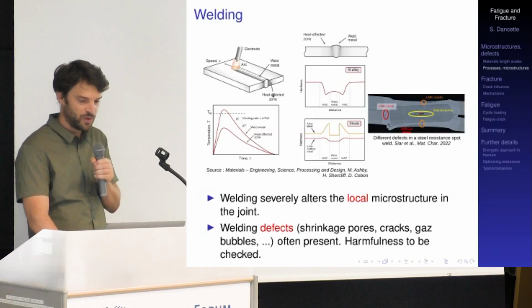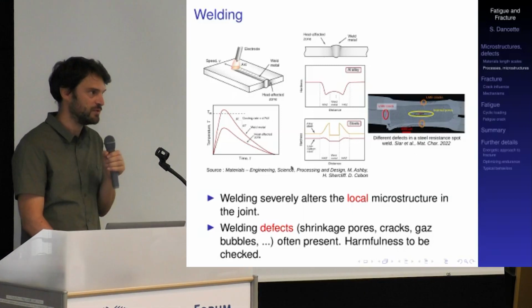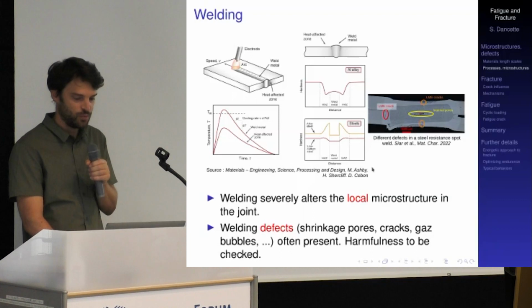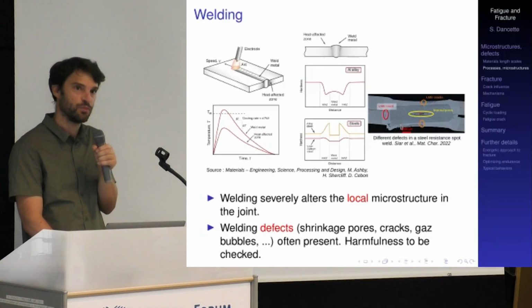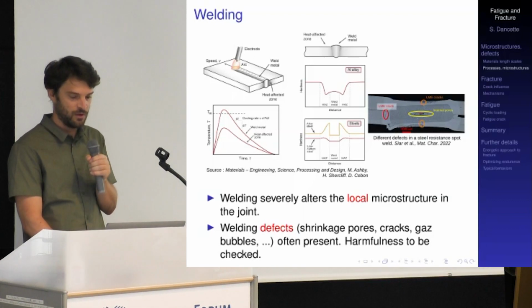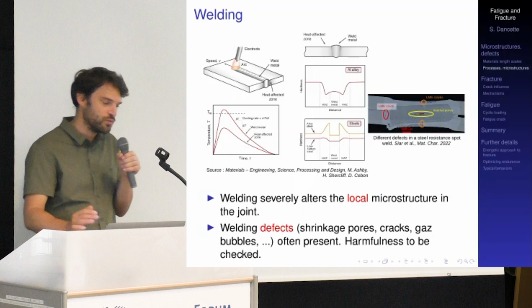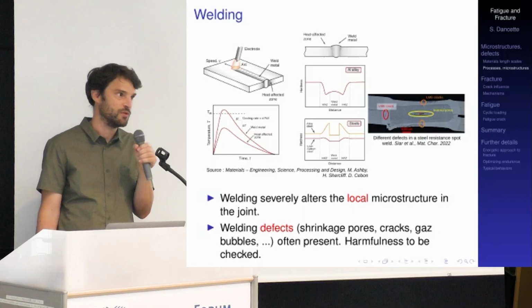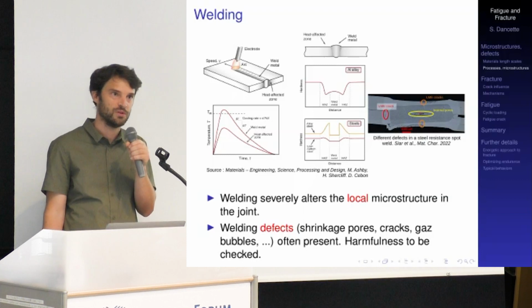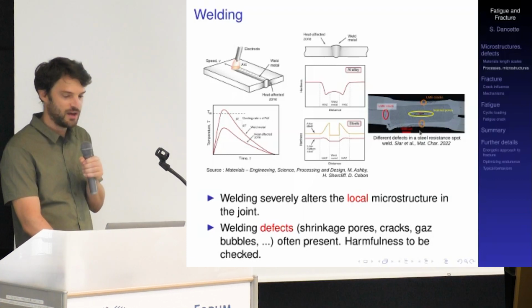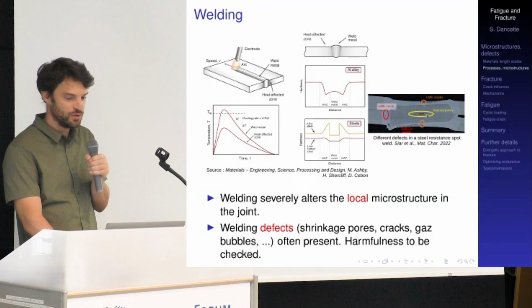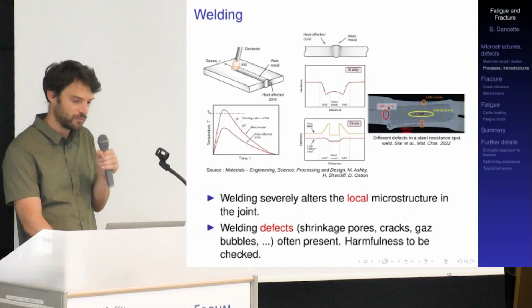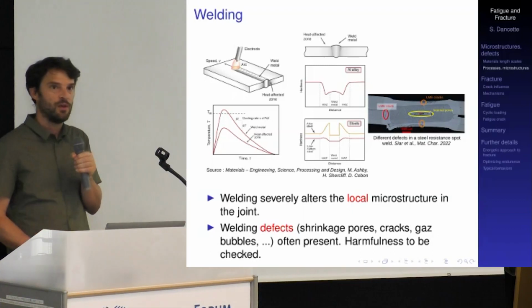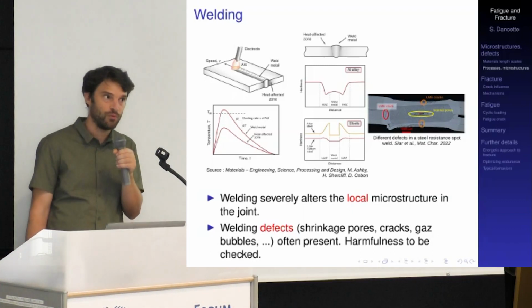But besides this, with the welding process, you will very commonly see several types of defects inside of the welds. And we have here the example of a resistance spot weld in automotive steels. Resistance spot welding is widely used as a common welding process in the automotive industry when you want to join automotive sheets. So in such a high strength steel resistance spot weld, it is not unusual to see several types of defects, such as liquid metal embrittlement cracks, for example, or internal pores, which again may be harmful to the mechanical properties.